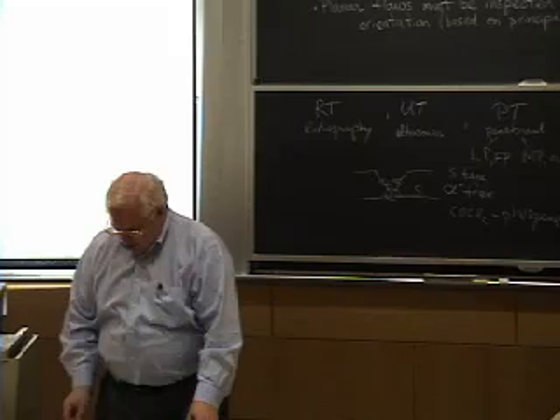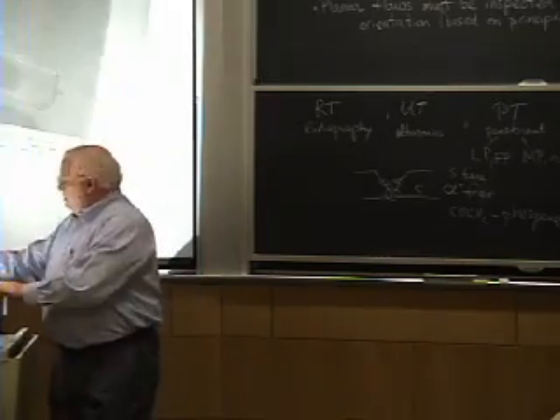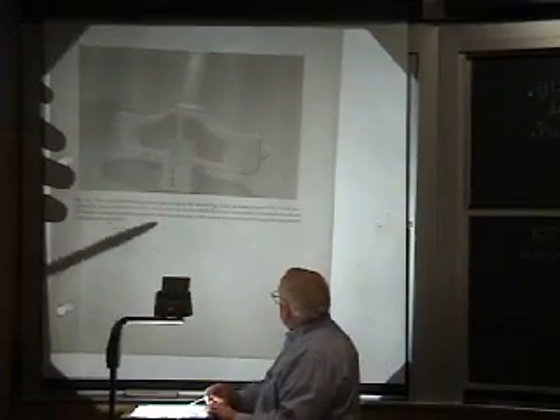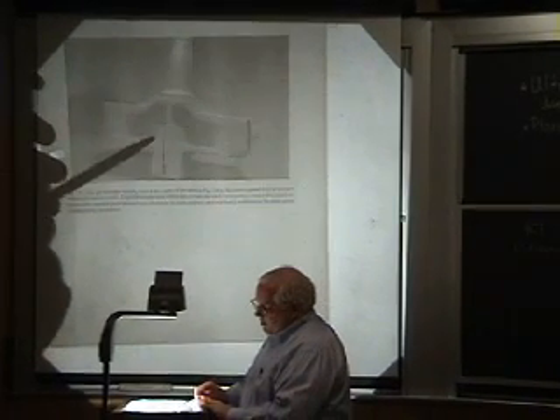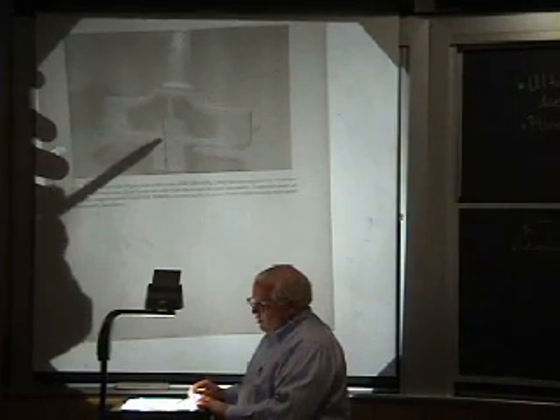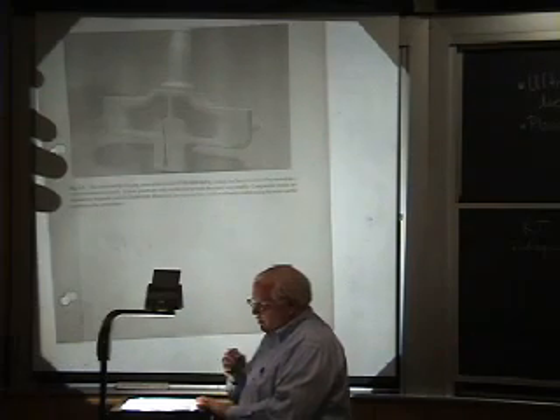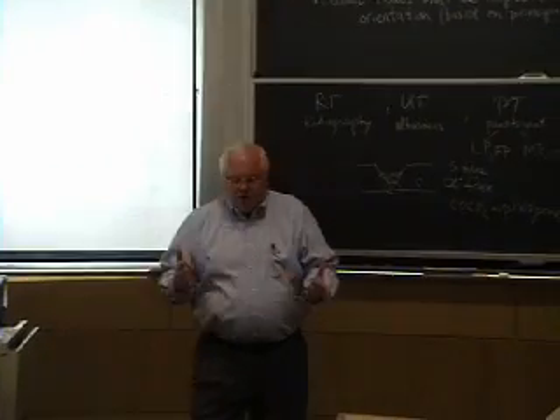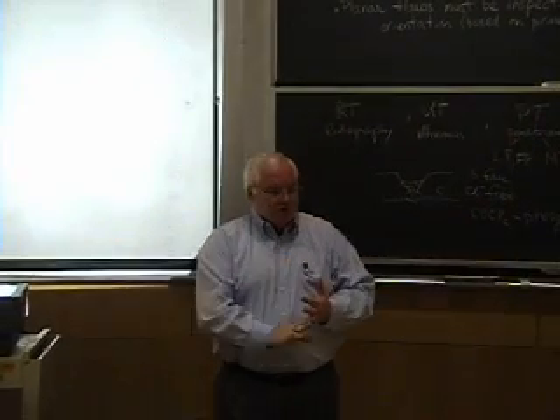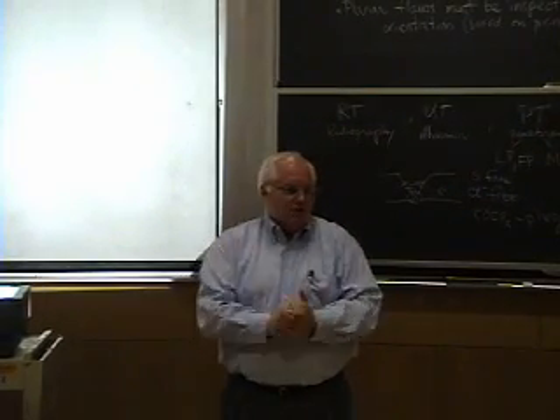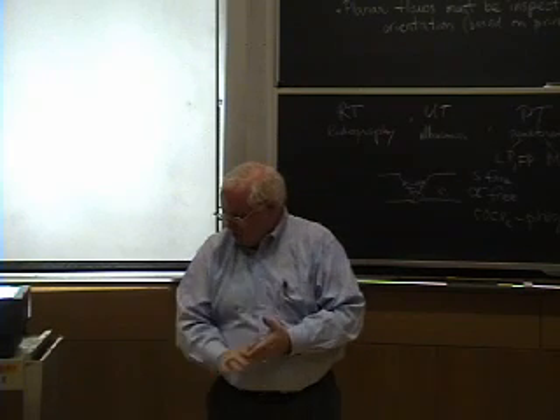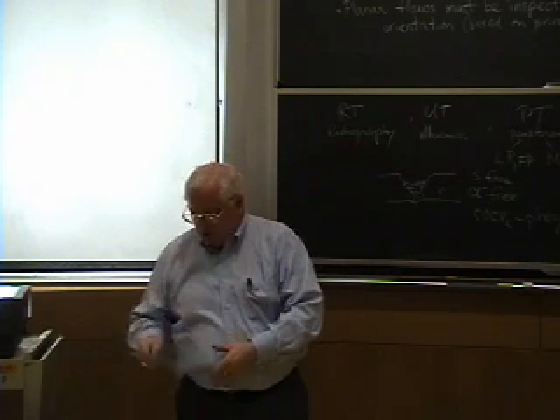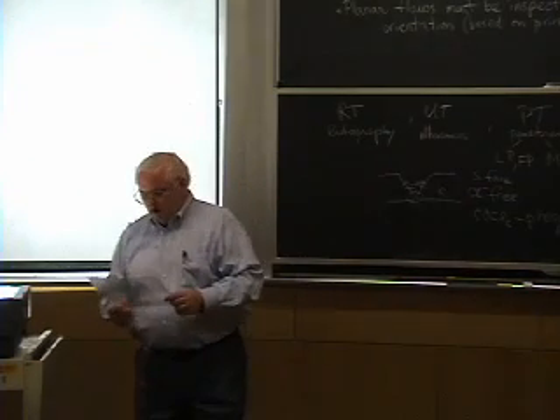Now, here's a picture of one of the red dye type of things. This is some sort of impeller or whatever, where they were looking for a crack. So you can see the white stuff that was sprayed around it, and there's the red dye that kind of marks it. Now, just because you get a red mark, it's an indication. Remember yesterday I talked about indications versus real flaws? You have to figure out whether the indication is relevant, whether it's a false indication. A lot of times you just have scratches on the surface, and scratches are not necessarily a relevant type of flaw and are not a defect.